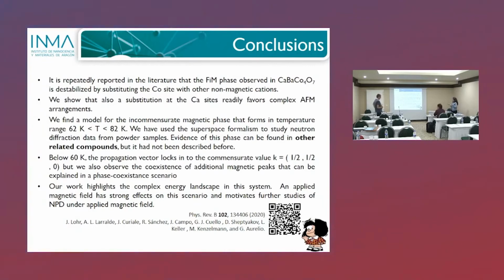The strontium addition really favors complex antiferromagnetic arrangements. We proposed a model for this incommensurate phase. And we also propose a scenario at low temperatures where there are two phases in coexistence, two competing phases.